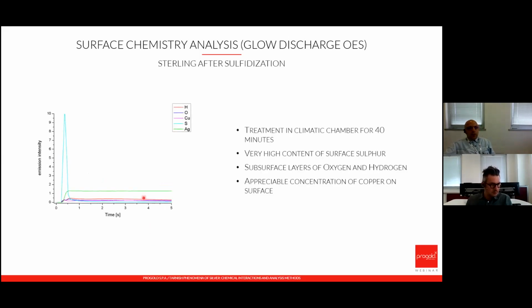Instead, the sulfidization test in the humid chamber enormously increases the sulfur concentration on the surface of sterling silver, and copper is also sensitively increased. As you can see from this mild peak within the big spike of sulfur, the copper is slightly higher than its nominal content in the alloy.